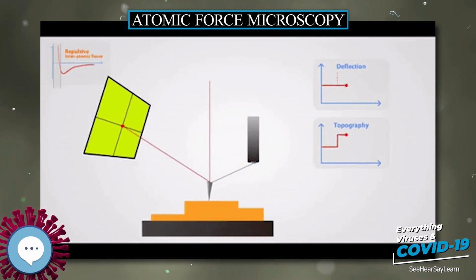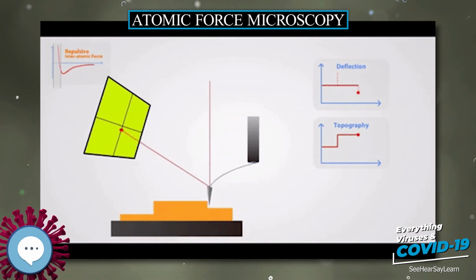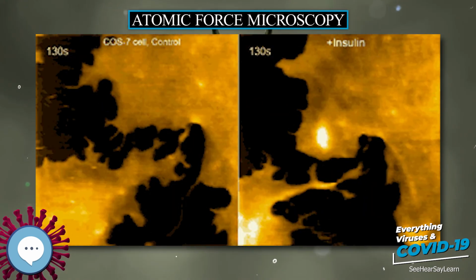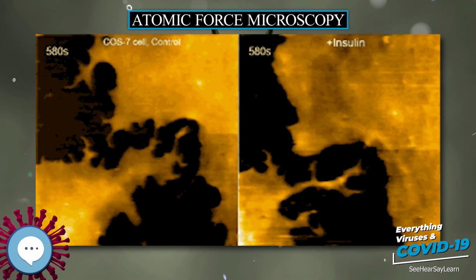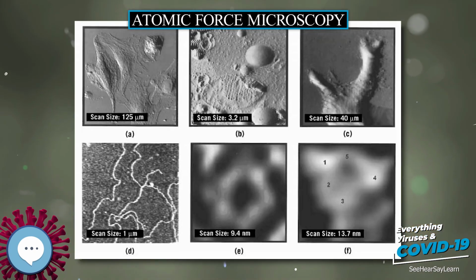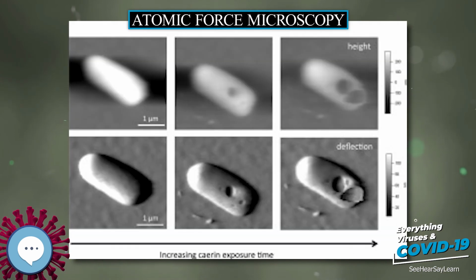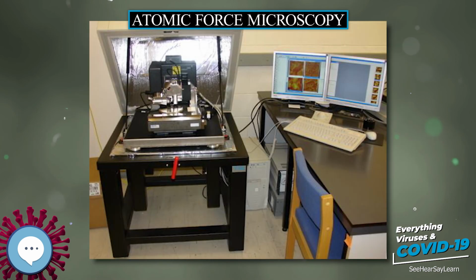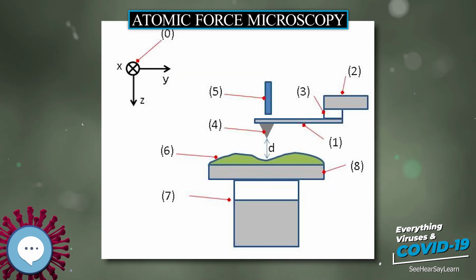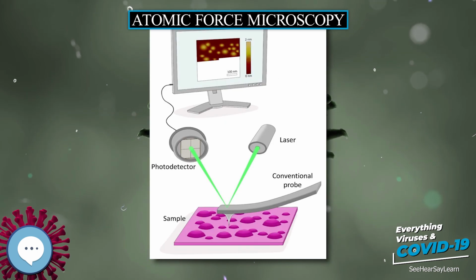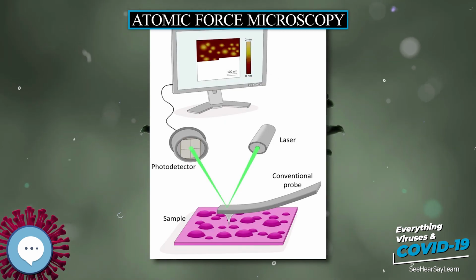Historically, a different operation method has been used, in which the sample-probe support distance is kept constant and not controlled by a feedback servo mechanism. In this mode, usually referred to as constant height mode, the deflection of the cantilever is recorded as a function of the sample XY position. As long as the tip is in contact with the sample, the deflection then corresponds to surface topography. The main reason this method is not very popular anymore is that the forces between tip and sample are not controlled, which can lead to forces high enough to damage the tip or the sample.